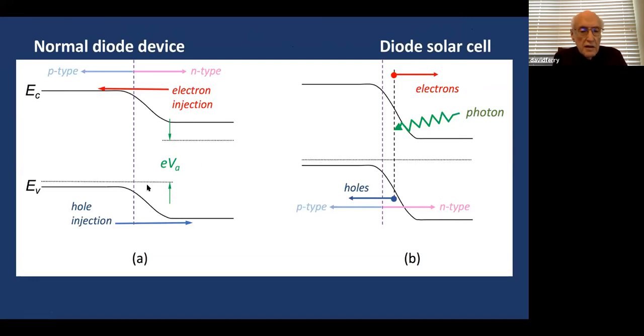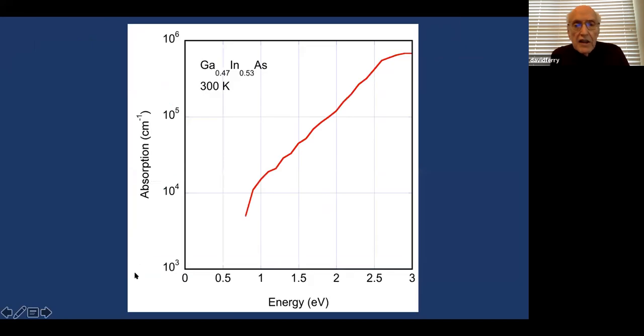Now, okay, all right, I'm back to this. For example, here's gallium indium arsenide at room temperature. This has a band gap of about 3/4 of a volt. And you can see up in here, 10 to the 5th, silicon will never get up to 10 to the 5th. It's down in this region because of its indirect gap.